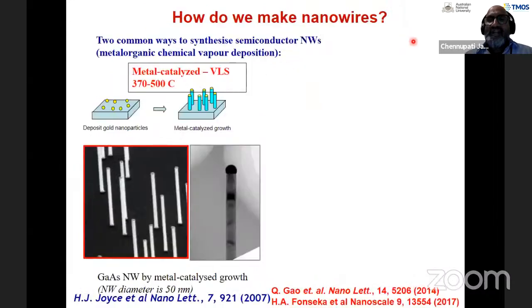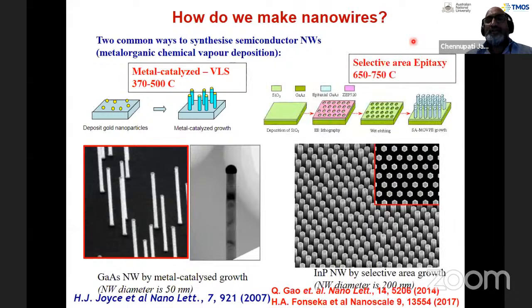Okay. So if nanowires are of so much importance, how do you make them? There are two main techniques which we use. One is called metal catalyzed VLS growth, and the other is called selective epitaxy. In this case, we take metal nanoparticles of gold, for example, 50 nanometers in this particular instance, and gold has a melting temperature of more than 1000 degrees Celsius. But once the gold reacts with gallium or aluminum or indium, the alloy melting temperature comes down to as low as 350 degrees Celsius.